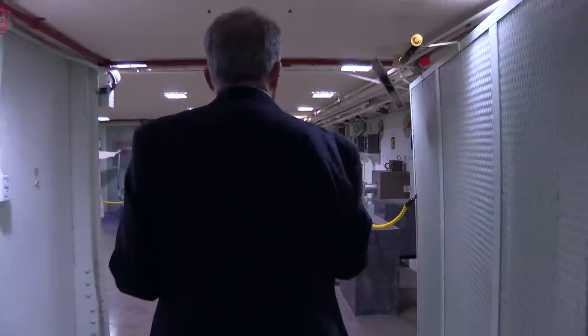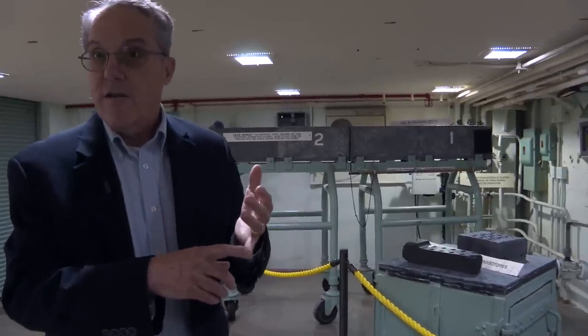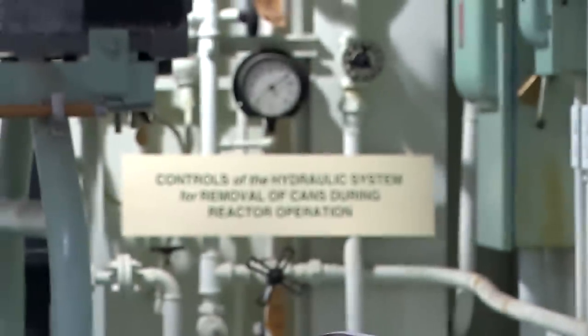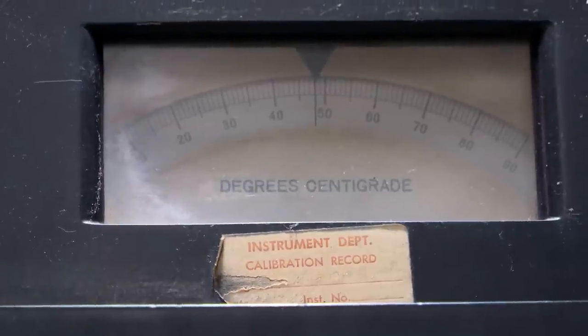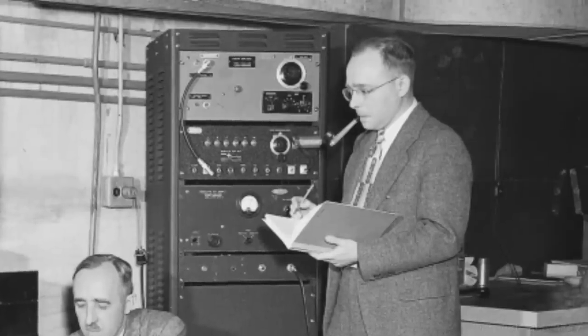This is at the midplane of the reactor, which means that the neutrons coming out from the reactor are going to come out horizontally. This is where the first neutron scattering measurement was done. We've got three ways of looking at the nanoscale or atomic scale properties of materials: one is with the electron microscope, one is with X-rays, and one that is probably not as well known is with neutrons. The neutrons associated with this reactor, which operates at thermal energies, have wavelengths comparable to the distances between atoms in solids. So you can do diffraction experiments from solids, which leads to different information than you would get with X-rays — information on magnetism and the dynamics of the motions of atoms. The first neutron scattering experiments were done here, and that led to a Nobel Prize for Cliff Shull, who developed neutron scattering in the 40s and 50s at this laboratory.